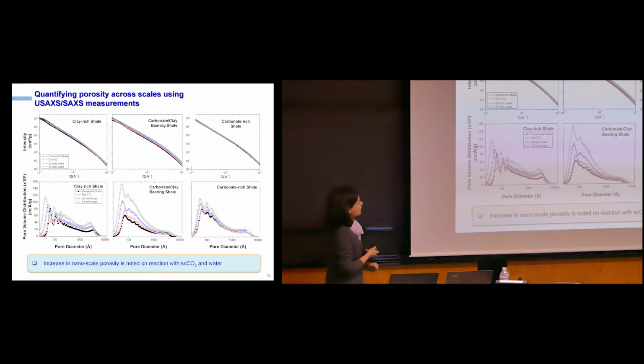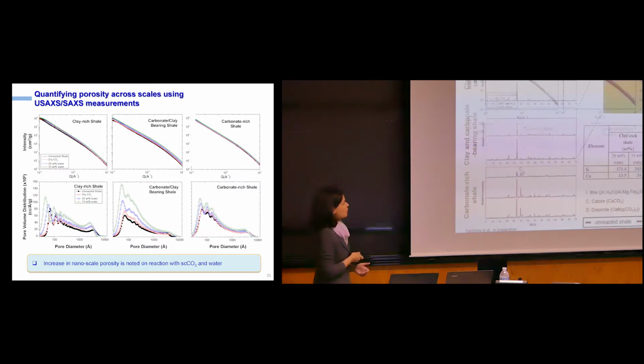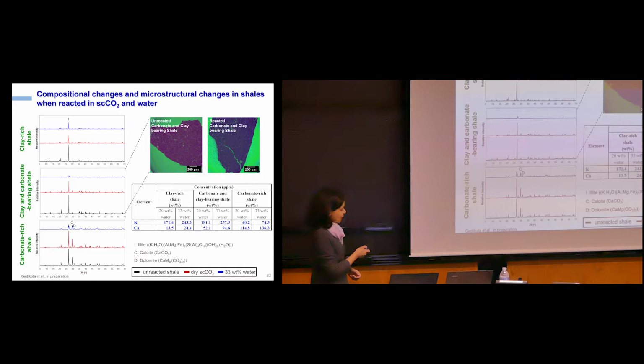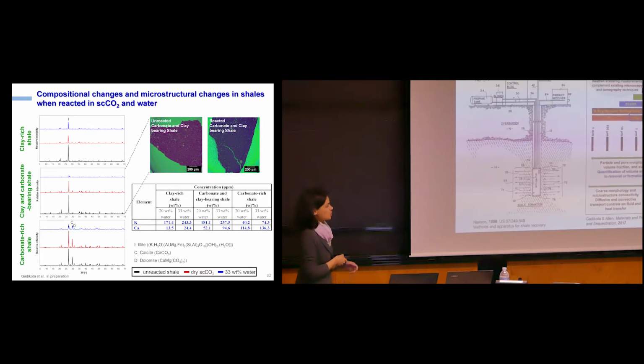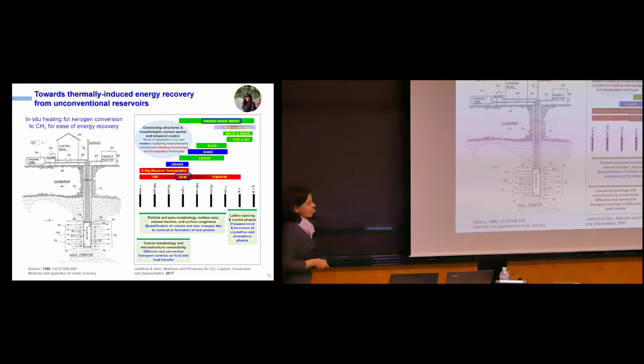So from this, we can see that my black is my unreacted shale. With just dry CO2, not a lot is changing to the pore structures. When we have CO2 and water mixed together, we see significant increases in the pore volumes of these materials. So clearly, having a mixture of CO2 and water is changing the pore structures of these materials. Turns out what we're doing is that we're dissolving a lot of the carbonates that are present in these materials. And these are some microtomography images. I'm not sure if you can see them very clearly, but I can tell you what we're seeing. Effectively, we're starting to see some directional type fractures in these materials as a result of exposing these materials to supercritical CO2 and water.